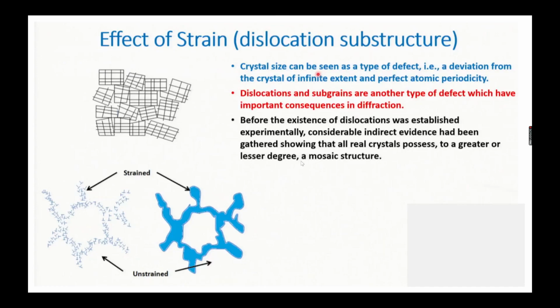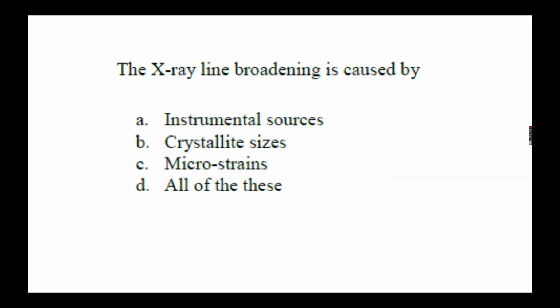And strain, when you create a strain, that will also cause line broadening. If you have applied strain in your sample as compared to your normal material, then there will be a change in your parameters, like your d value, because the arrangement of atoms will change when you apply the micro or the macro strain. So this will also change the broadening. So all of this, strain, crystallite size, micro strain, and the instrumental source, will affect the line broadening in X-rays. So the answer is D.